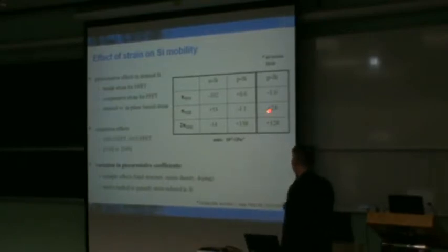And what I'm showing here in this column corresponds to data that was generated a few years later that showed that within the inversion layer that we really cared about, we can see some wide variety, particularly in the longitudinal direction and the transverse direction, on the values. And so the question is, what number do you really use here for these types of quantities? And what I would argue the net result is that we have to come up with another way rather than pure electrical measurements to be able to quantify the stress that exists within these systems, to have any hope of understanding what would be happening and to be able to predict that in future devices.